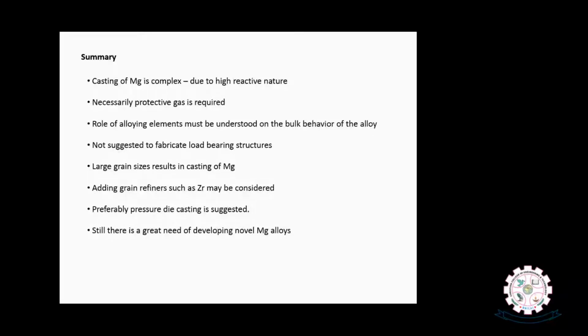The role of alloying elements on the bulk properties of the alloy must be understood while selecting the percentage of alloying elements. It is not suggested to fabricate load-bearing structures from cast structures, since cast structures themselves are not good compared with the wrought structure, in general material science principles. And when it comes to magnesium, because of its HCP crystal structure, cast magnesium components are not suggested for load-bearing applications, and large grain sizes result in casting of magnesium.